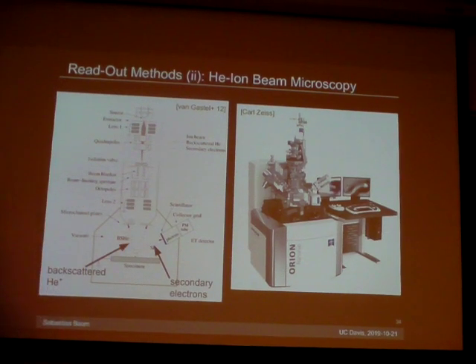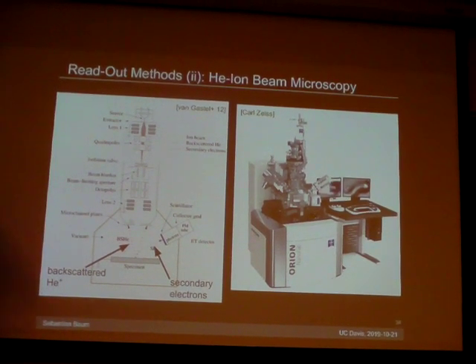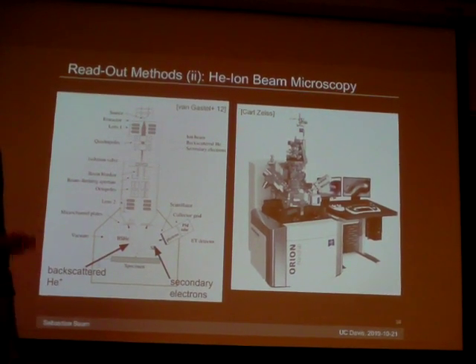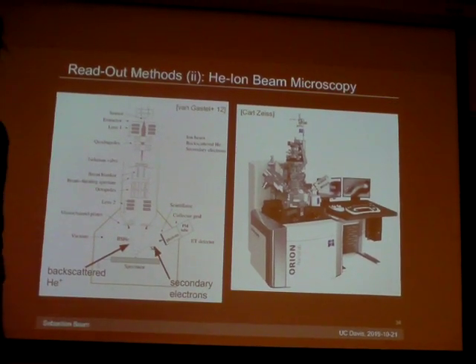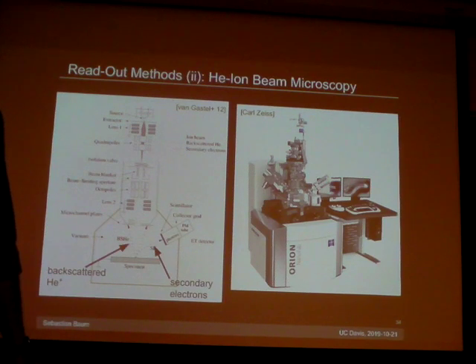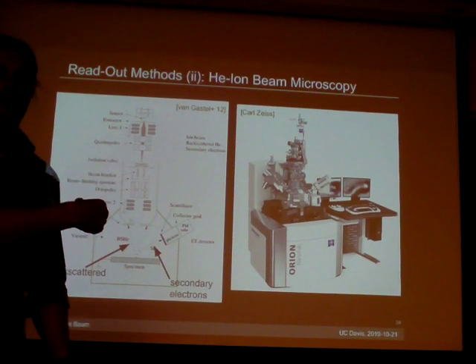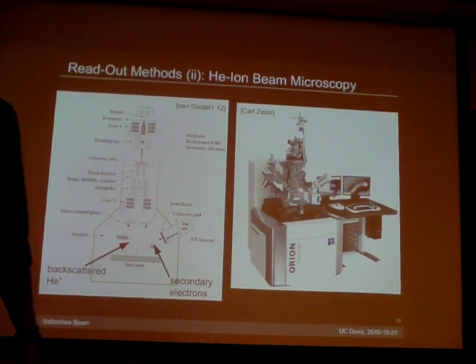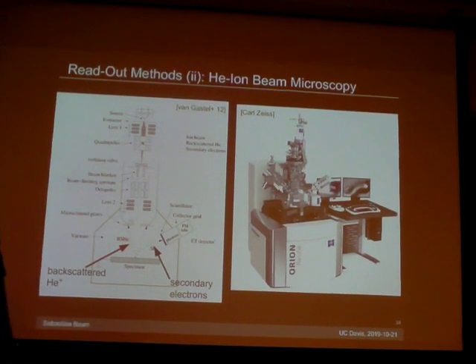You can use a technology like this. You can do something very similar with electron microscopy. You read this out layer by layer. So effectively in the end you're going to get a 3D picture of your sample, and the resolutions you can achieve are on the scale of nanometers. It's the best resolution that makes any sense for this, because if it's even shorter than that, there's no point calling it a track anymore. However, the price you have to pay for this resolution, of course, is you can only process a much smaller sample. So we think you can do something like 10 milligrams with this in a time frame of a few months.